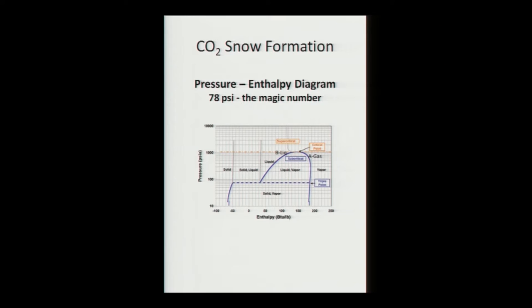So you have a solid phase hitting the surface, and when that happens, pressure increases. As the pressure increases enough, you exceed the 78 psi again, and you form the liquid phase. Liquid CO2 is an excellent solvent for hydrocarbons. So you're essentially doing a solvent cleaning on the surface as you're physically knocking the particles off.